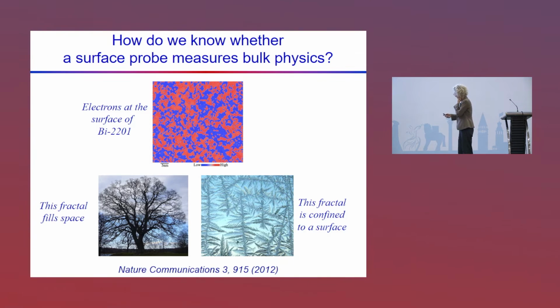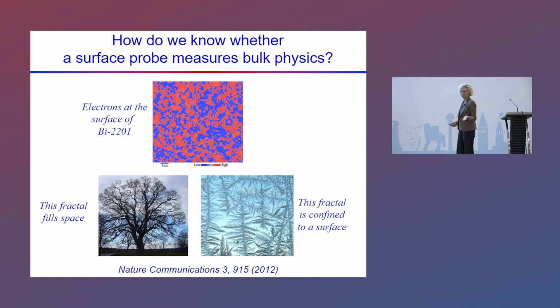So here's my analogy for why this should work. You're used to diagnosing fractals out of windows. Sometimes you look out of a window and you see a tree, and that's fractal. But you know that tree fills space. You can just tell by looking at it, right? In your experience with trees, it fills space, and then you're seeing the 2D projection into your eyes. This is a fractal that doesn't fill space. This is frost growing on the window. It's a 2-dimensional fractal, and it looks completely different.